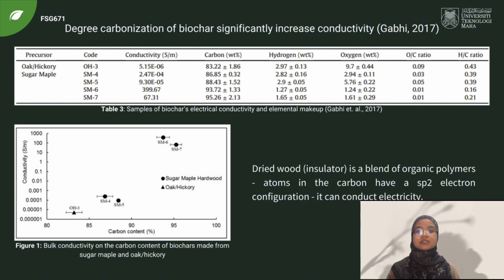Nevertheless, the sample with the highest conductivity, SM6, was not the one with the greatest carbon content, indicating that the biochar's conductivity is also influenced by other factors. Remarkably, the conductivity ranking appears to be in line with the O per C and H per C atomic ratios, but in opposite order. Hence, conductivity decreased as their ratios increase.